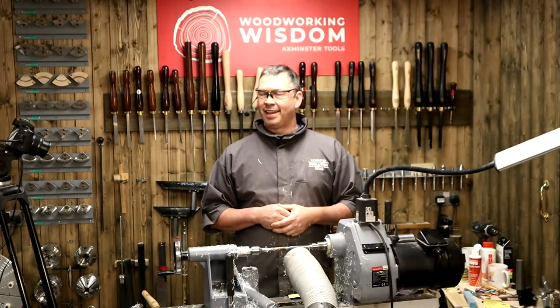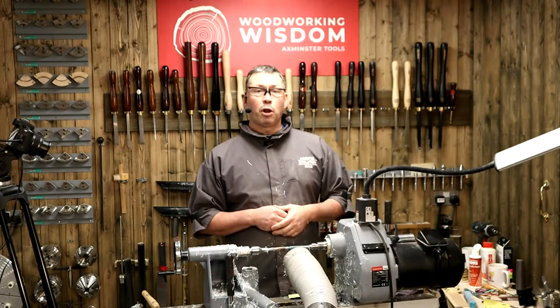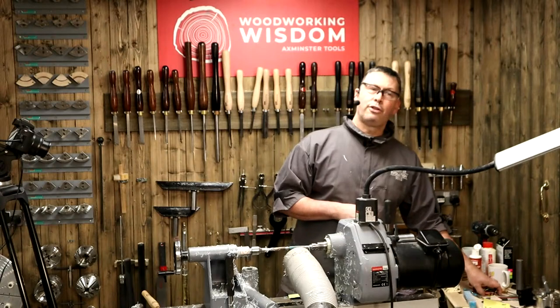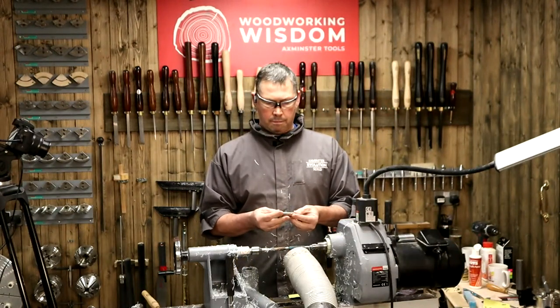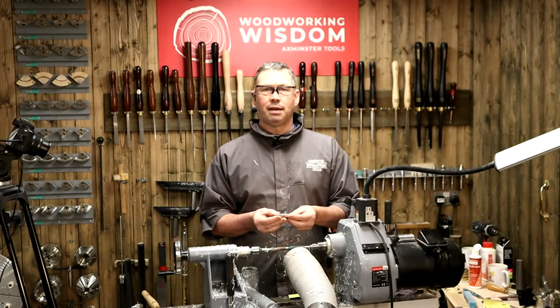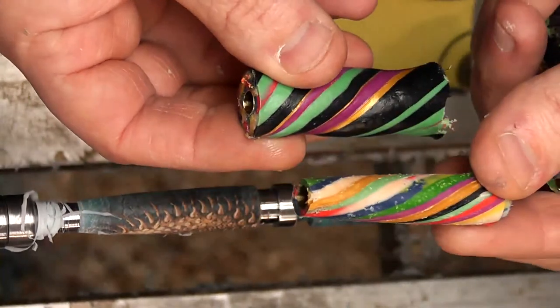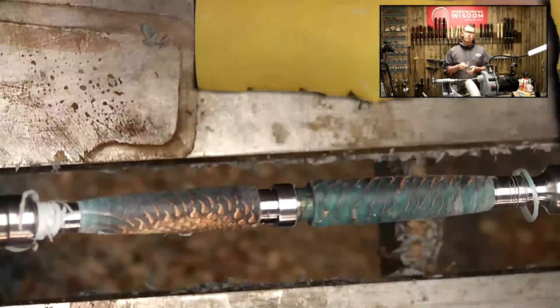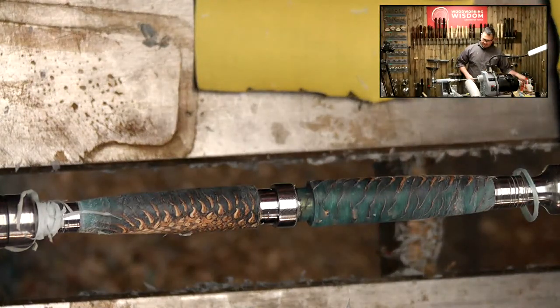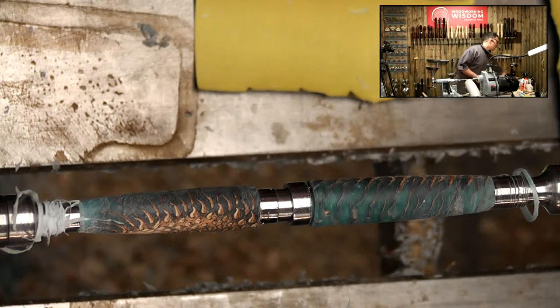Yes, Ben. And then the unsuccessful blank, can we just remind us what that was made of? Yeah, that was polymer clay. So things like Fimo, kids' clays, that sort of stuff. But it's designed to be baked in the oven, and I case hardened it. I baked it far too hot, and so it really burnt the outside, but it didn't really do anything to the inside. I should have done it a little bit cooler for a lot longer. So that'll be next week's plan. I'm going to put dust extraction on now, but Ben, keep asking questions.